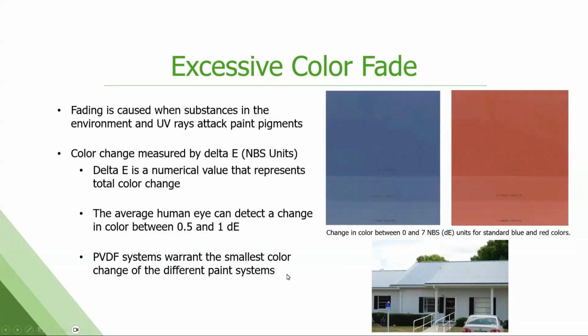Color fade, however, this is a big one, right? This is probably that and your paint sticking long term, but color fade is a big deal. Of course, fading's caused when the pigments are attacked by UV and start to lose their color. We measure it by delta E. Again, that's a numerical value that represents the total color change from where it started to where it is now. Human eye doesn't start to see that until you get to 0.5, maybe up to 1 delta E and beyond. PVDF systems, warranties allow for the smallest amount of color change. So the warranties are not saying that there won't be any color change. It's saying you won't have color change beyond a certain delta E value.